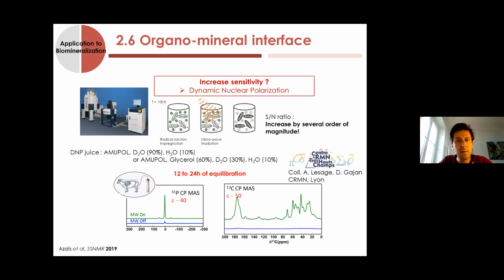So it's interesting to turn to another technique called dynamic nuclear polarization, a recent technique that allows you to increase the signal-to-noise ratio in NMR experiments by several orders of magnitude. You achieve that by mixing your sample with unpaired electrons, meaning through a radical solution, and then through microwave irradiation you transfer the magnetization from the unpaired electrons to your sample.